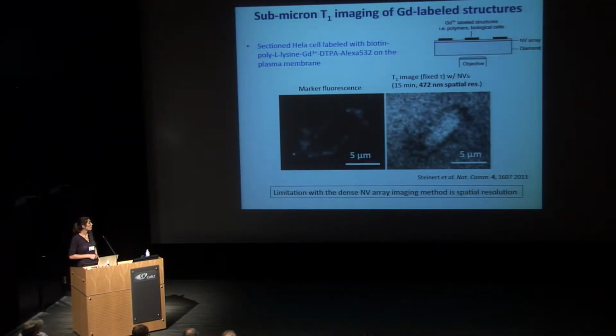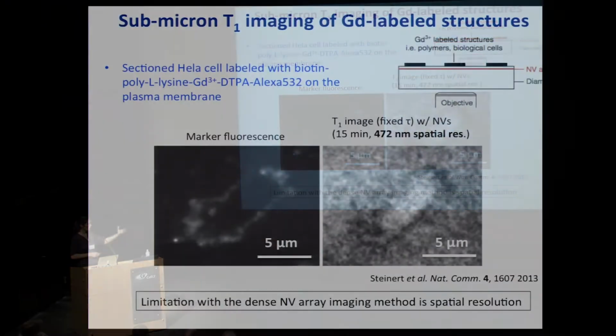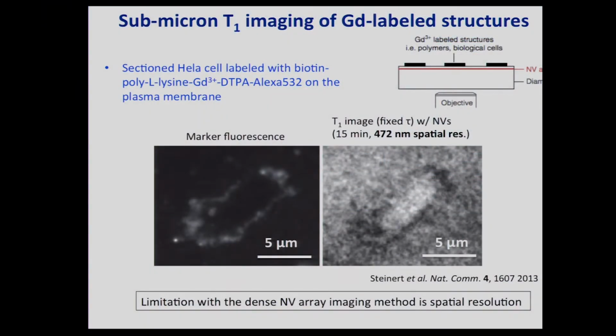I should mention that there was an experiment last year done in the group of Jörg Wrachtrup in Germany where they used gadolinium, this type of relaxation imaging, to image just the structure of a cell. They took a HeLa cell and labeled it with this gadolinium complex, which also had a fluorescent marker attached to it, this Alexa fluorescent marker. And so here, if they just take an optical image of the marker fluorescence, they see the outline of the cell because this complex is specifically attaching to the cell membrane.